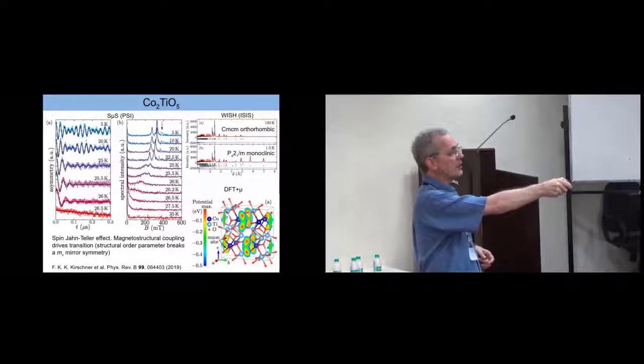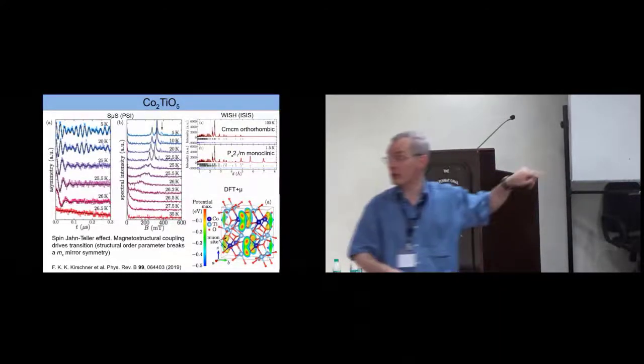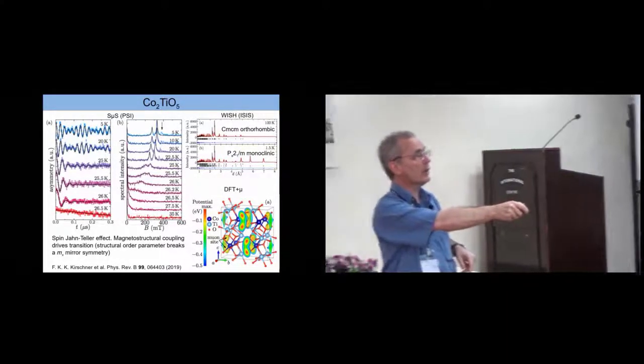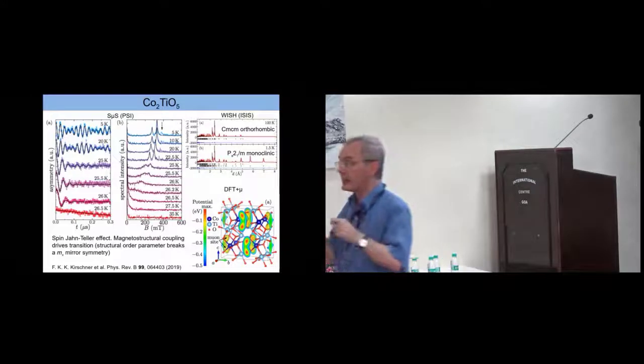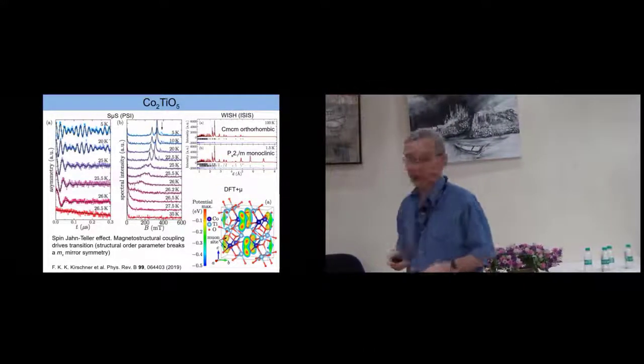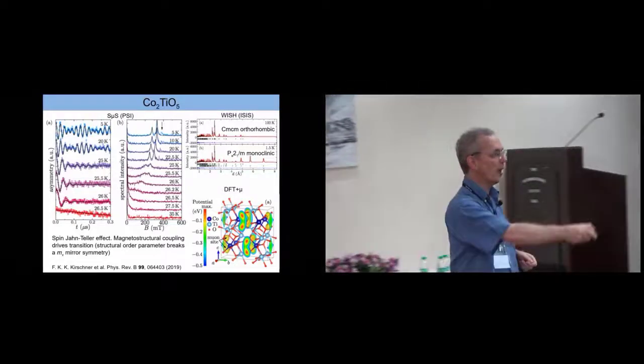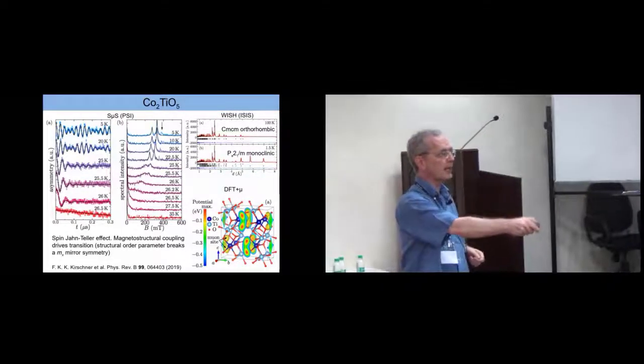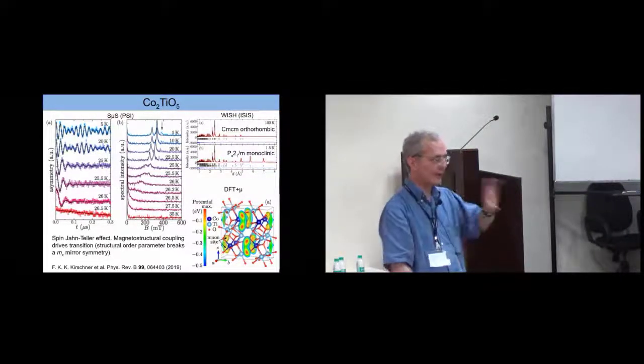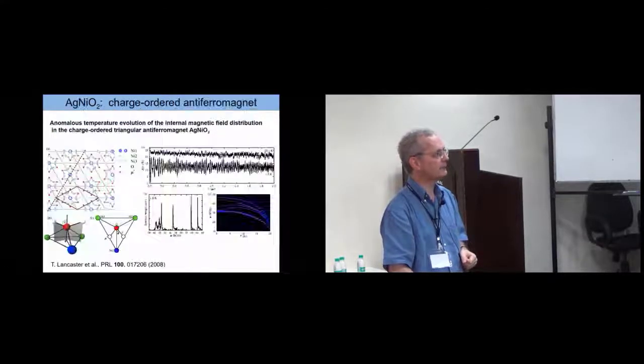What you can see at low temperature are now two oscillations, and if you Fourier transform it, you see two peaks. So this is a case where there are two different muon sites, at least with respect to the magnetic structure, and this is something that we're able to study using DFT plus mu. I'll explain more about that later.